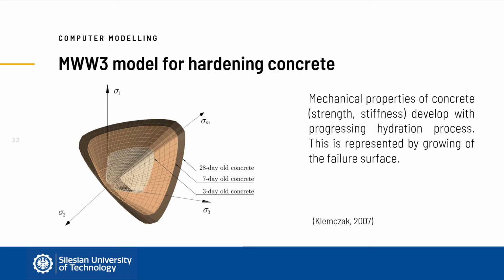It is interesting to add that failure criterion can be used not only for mature concrete, but also for concrete in the hardening phase. Since the surface is defined based on the strengths of concrete, and given that these strengths develop with progressing cement hydration, this is represented by growing of the failure surface. From the point of view of modeling, the calculations of hardening concrete are performed with an incremental approach for discrete time steps. In each step, the failure surface is redefined according to the assumptions of the failure criterion for the current values of the strengths.